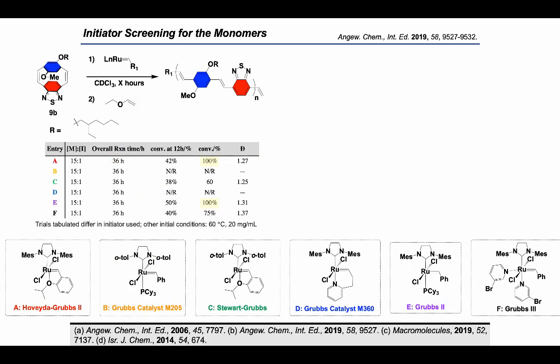We began by screening various Grubbs initiators to ensure our polymerization would be complete and successful. We found that for the monomers shown, the entries A and E, for Hoveyda-Grubbs 2 and Grubbs 2 respectively, yielded complete conversion after 36 hours. So these 2 seemed to be viable initiators moving forward.